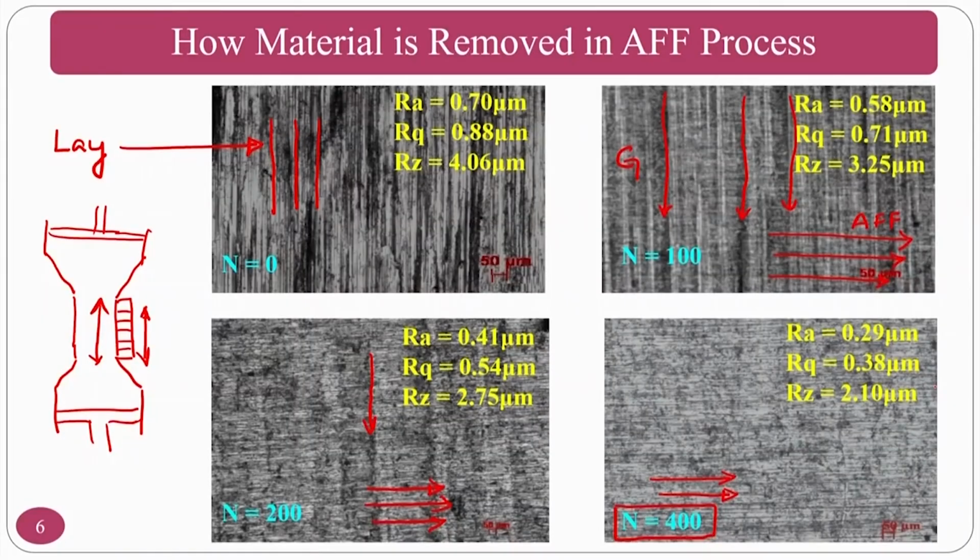So, do not go by the number of cycles many times. This always depends on your medium cylinder capability. If your medium cylinder capability is too small, your number of cycles will go up. If your number of cycles goes up, your medium gains some temperature because of the shearing action at faster rates. So that's all. Some problems will be there at laboratory scale. However, the laboratory scale setup that we have used in this particular experiment is economic to produce. That's why this is done at the laboratory scale itself.